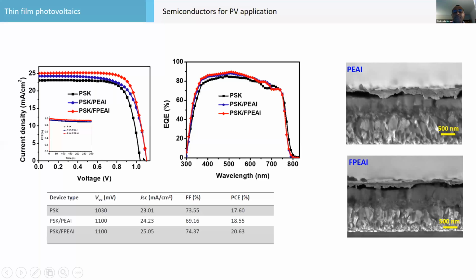And always we have a significant increase in the voltage. So the voltage is 70 millivolts higher. The current is similar, so you cannot see improvement in the current here. This is a cross-sectional diagram of a bilayer perovskite structure. So this is a tin oxide, there's a perovskite, and then you have a very thin layer. You can see it's buried between. Here is a thin layer of